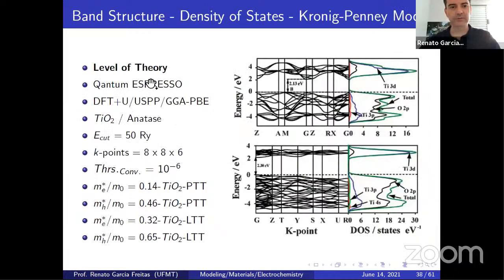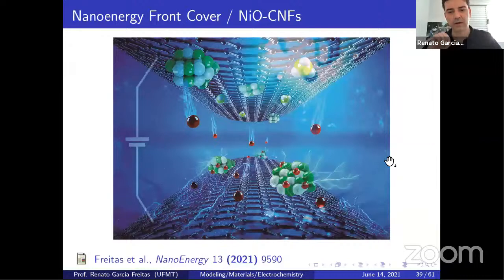And also we made some quantum espresso computation. We have the band structure with a broad band here. The derivative of the band gives us the effective electron and hole mass. So for the previous thermal treatment compared to the later, we observe a decrease of the band gap as well, and of the mobility. The electron mobility is higher for the previous than the later, 0.14 and 0.32. For the hole as well, the mobility of the hole is higher than the electron for sure, and lower for the previous compared to the later, 0.65. Also here, a higher contribution of oxygen and a higher contribution of titanium. I don't know what about my time, but I think that's what I want to say.